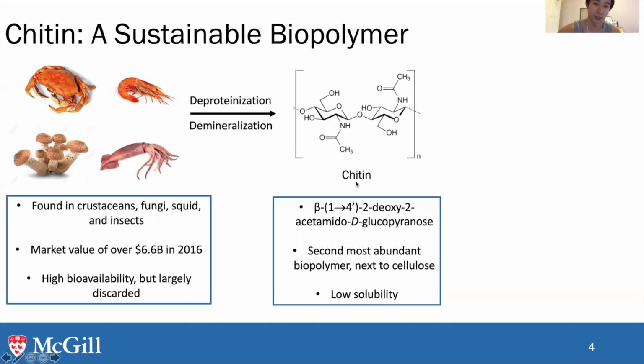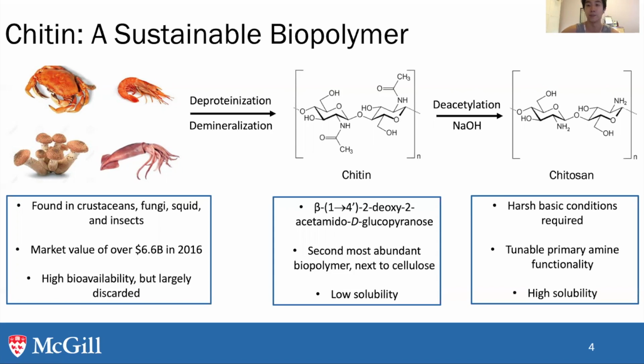However, it is highly insoluble in aqueous media. So to provide more applicability, you can deacetylate this acetamide unit into the primary amine group. This is what we call chitosan, one of the derivatives of chitin, and it uses basic conditions to deacetylate. What we're left with is a highly soluble as well as tunable amine functionality in this chitosan polymer.